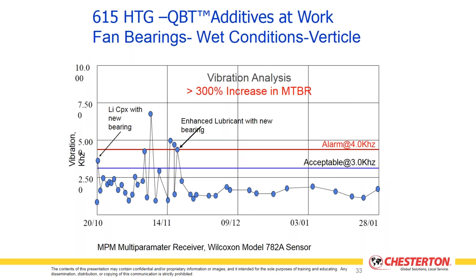And as we approach this methodology of selecting lubricants for environmental conditions, we might be able to achieve something like we have in front of us here, where we took some fan bearings in wet conditions, vertically aligned, and where they were using a typical lithium complex grease and they were having this service life as indicated on this scan, relatively short. The bearing was changed, a different lubricant was used with enhanced properties to handle water, corrosion, anti-slump for vertical. And we actually started to get 300+% increase in bearing life simply by looking at what does the piece of equipment really need versus what was in the OEM book.